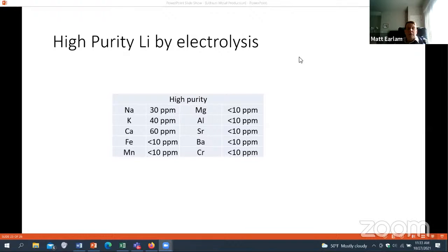So by improving the brine quality and therefore the lithium carbonate quality, we can actually produce lithium at pretty high purities, up to like 30 ppm sodium, down to 40 ppm potassium. These other transition metals less than 10 ppm. So the big contaminants are sodium, potassium, calcium. All of these come from the brine. And then the magnesium, but they've been able to produce that as well. So that was kind of interesting that they've been able to do that.